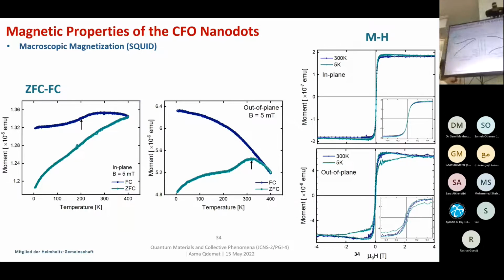Okay, so what we also performed, to study the magnetic properties of these cobalt ferrite nanodots, we performed the magnetic measurements in a SQUID, and I was interested to study the magnetic moment along the plane and perpendicular to the sample surface, out of plane. So what I did, I measured magnetization as a function of temperature, as we call zero field cooling.